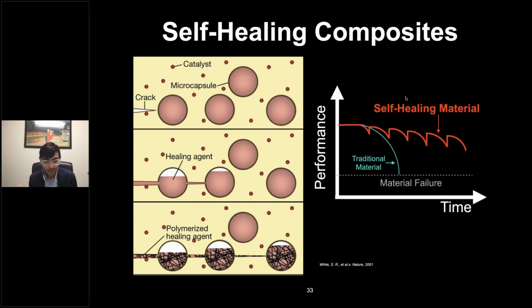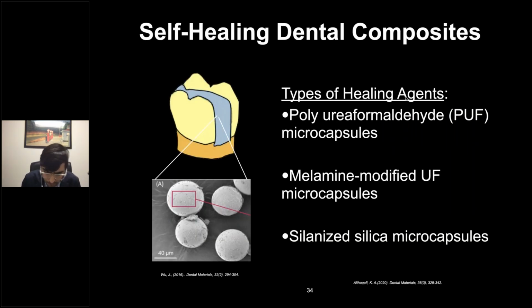And by doing that, we'll mitigate the crack formation and improve the material service life. This is shown by this graph: you have performance and you have time. A traditional material, the more time goes, the performance decreases. But if you have self-healing materials, you expect that every time these microcapsules burst, you have an increase in performance, and with time, you can also have an extended life.